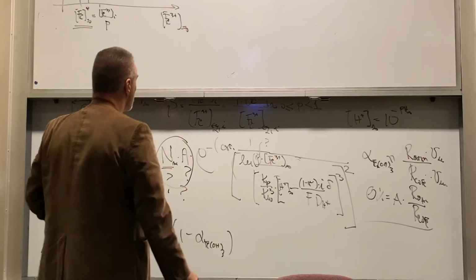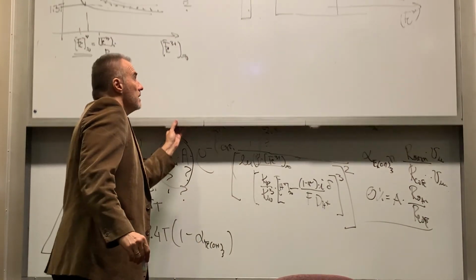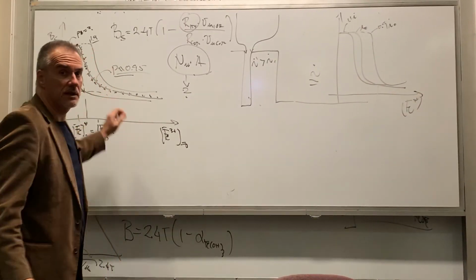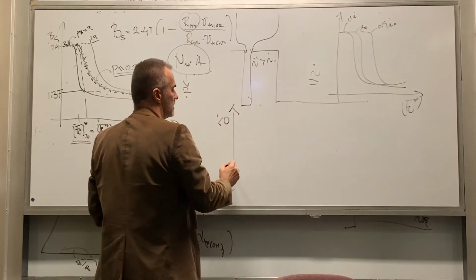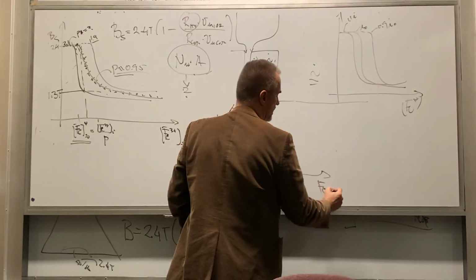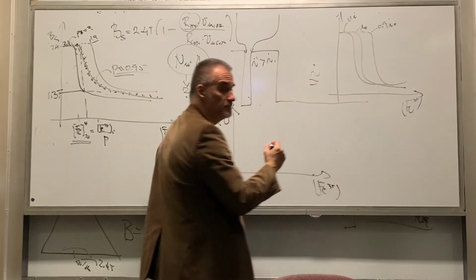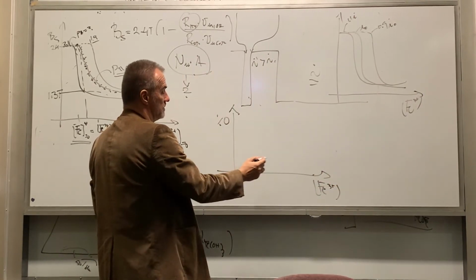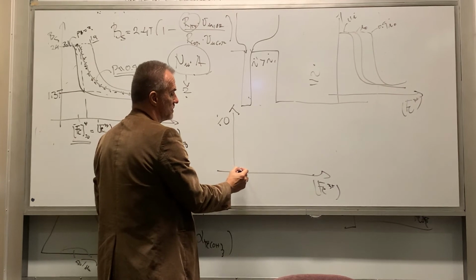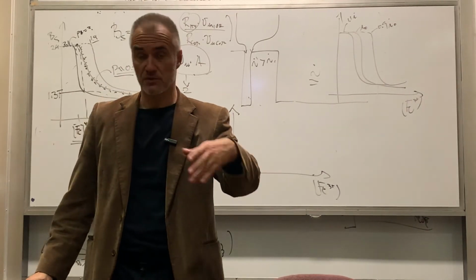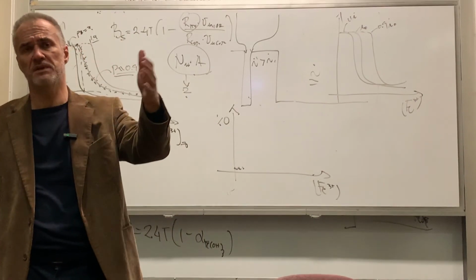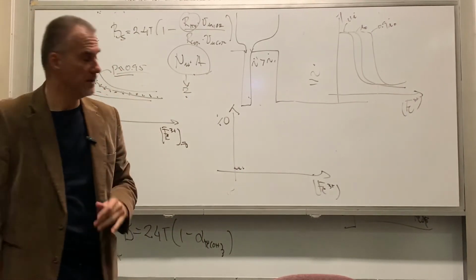And I can generate another measurement. Instead of measuring the magnetic moment, I can measure percentage of oxygen as a function of iron 3 in my solution. And obviously, there will be some residual content of oxygen which is unrelated to iron 3 hydroxide precipitation, which could be trapment of the ions, sulfates, whatever.